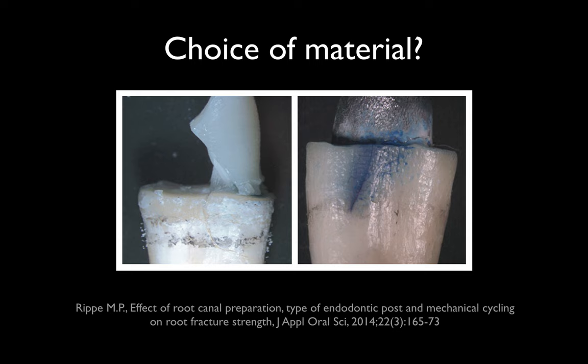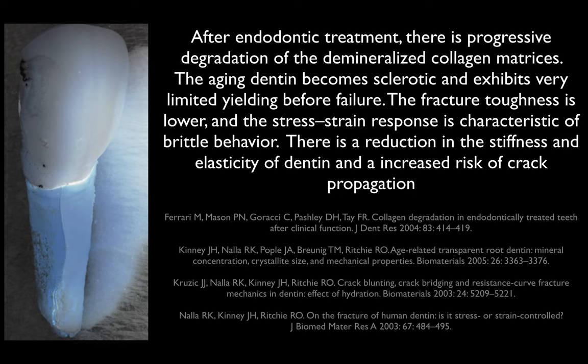How about choice of materials? Many of us have heard that only metal posts crack teeth and fiber posts don't. But research showed that's not true — you can get fractures of the tooth using any material. After endodontic treatment, there is progressive degradation of the demineralized collagen matrices. Aging dentin becomes sclerotic and much more brittle, resulting in increased risk of cracks and propagation, and we have to be aware of that.